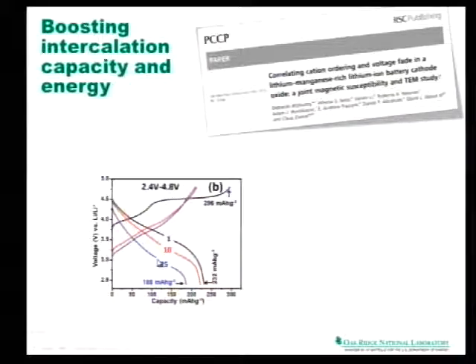And that is a nightmare for Burak. If he needs to design the power electronics for a charger to measure state of charge of this battery, he has no way of doing it. Because if you look, you never want to discharge your battery all the way to the end of that knee. You want to cut it off somewhere here. And when you look at that, you're measuring voltage, and you believe initially with a voltage of about 3 volts, you're at about 90% state of charge. 90% depth of discharge.